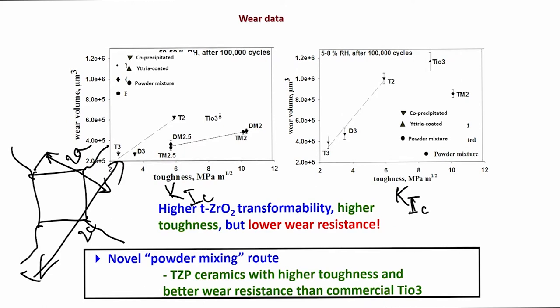Now, what you see is that wear volume increases as you increase the fracture toughness. That is true for the commercial powders, ceramics which are made from commercial powders. Now, from our own powder mixtures like TM2.5, TM2 and so on, you again see an increasing trend of wear volume with fracture toughness.